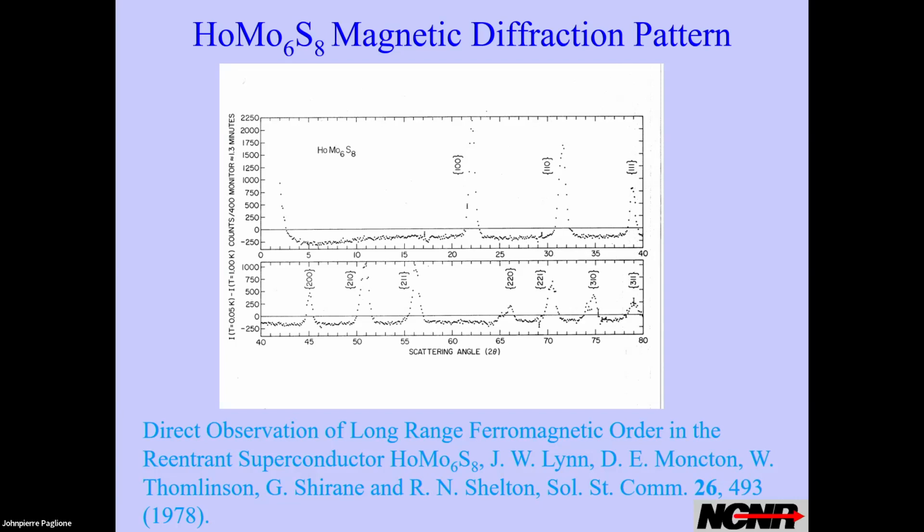And so you get this magnetic diffraction pattern with all these very nice peaks. And you notice you also have a deficit of scattering here, which tells you that the magnetic moments scatter in the paramagnetic state, but they're just Q independent. But when you subtract that off, you get a negative scattering, an absence of scattering.